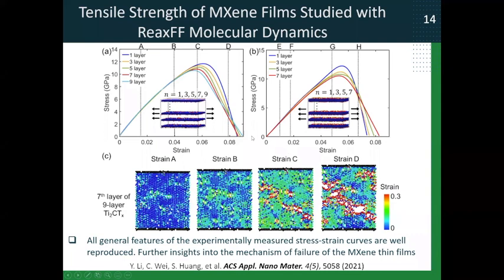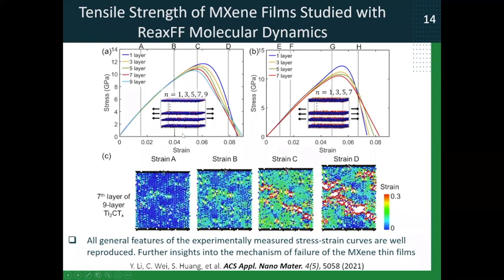We were very encouraged by this fact, and then we started to look into mechanisms of failure, and indeed we observed that in the stack, say for example, when we have say 10 layers in the stack, the failure starts in one layer first, and then it propagates to the next layer and to the next and to the next. So this is what is responsible for this softening behavior, where your material becomes softer, but it doesn't fail completely. Okay, so it was confirmed with modeling at the atomistic scale.